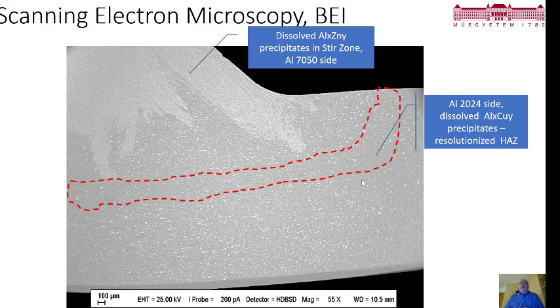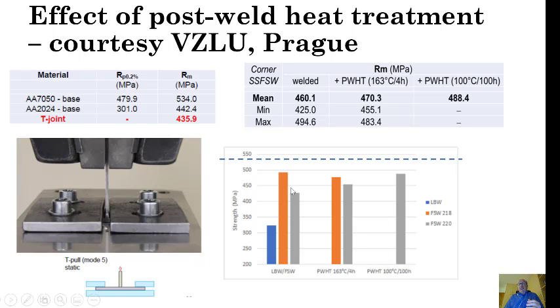So when we looked at the scanning electron microscopy, the EDS picture, we found something very interesting, that in the area which actually is zinc rich, coming from the aluminum 7050 side, we have extremely fine precipitates. We barely see them here, while the aluminum copper precipitates have almost dissolved in this heat affected zone. So that brought us to the conclusion that we should not wait 6 months to a year. Remember, this is a naturally aging alloy. 7050 is. Aluminum 2024 isn't, but you probably don't want to normally post-weld heat treat. So we said, hey, why don't we use a low temperature, kind of baking it at 163 degrees for 4 hours, and you see that properties actually improved by aging.